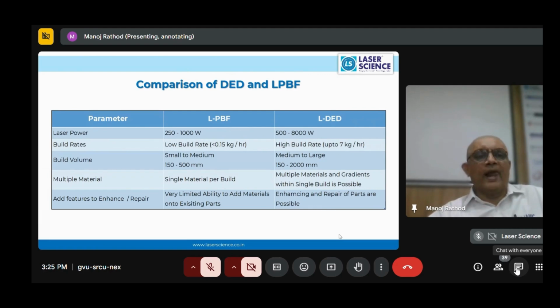Then when we talk about the building rate, you get a low build rate volume with the laser powder bed fusion, 0.05 to 0.15 kg per hour. And when you talk about the DED, it is a high build rate volume, up to 7 kg per hour. Build volume is small to medium, like you can design the smallest parts around 150 diameter, from a tiny pin to big parts, that can be printed with the LPBF. But in the laser direct energy deposition, you can print medium to large size parts, from 150 up to 2000 millimeter, or 3000 millimeter also now available.